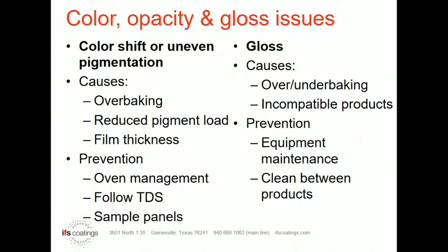Another factor could be the coating supplier trying to cut costs by removing some pigmentation from the powder. For example, creating an unnatural white pigment by replacing a percentage of the titanium dioxide with calcium carbonate, which is a filler. If this is a new problem with a product that you've ordered before, or you've asked for some value engineering to be done to the product, maybe talk to your powder supplier about any changes that might have been made.